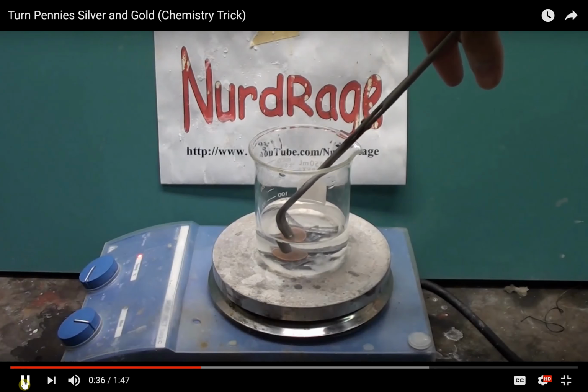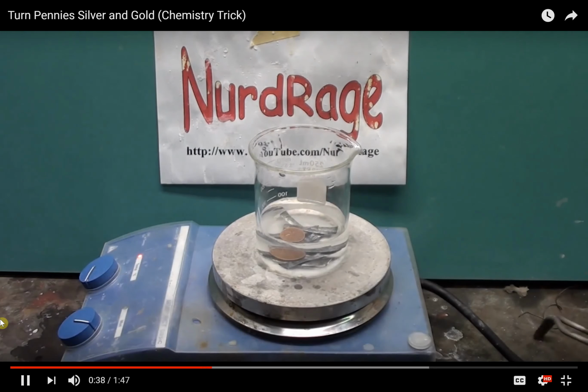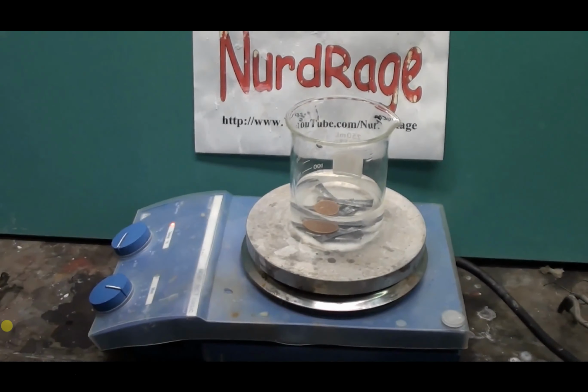Okay, let's see if you got it right. What's happening is the zinc is reacting with the copper and dissolving, while delivering electrons into the copper. The copper, now charged with electrons, will reduce free zinc ions into zinc metal on its surface, giving a silvery color. This takes about 10 minutes, so I'll skip over that. Here you can clearly see the more silvery color of the penny.